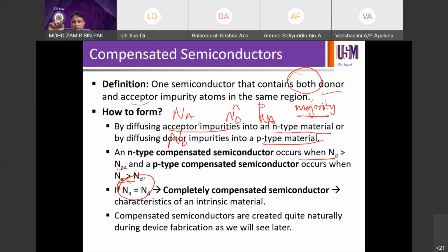D, right? Good. N-type, we're talking about ND as the dominant carriers, right? We learned that n can be approximated to be ND because ND is way higher than ni. We learned in the last class, right? When you start off with ND, and then you incorporate more Na, you incorporate more p-type into this n-type silicon, and up to the level when Na eventually equals Nd, you are going to end up with a completely compensated